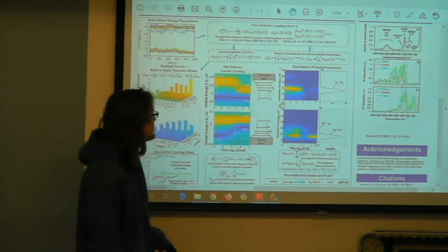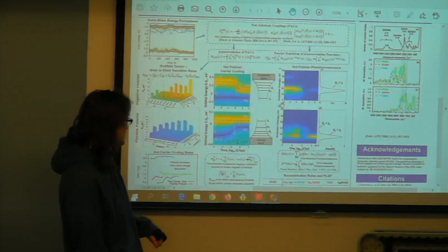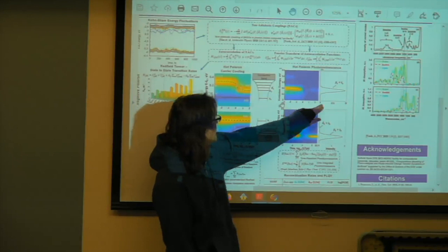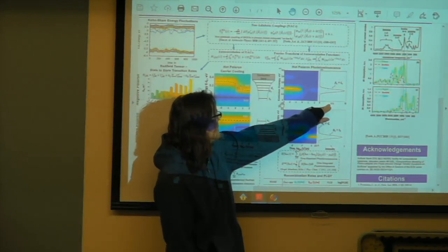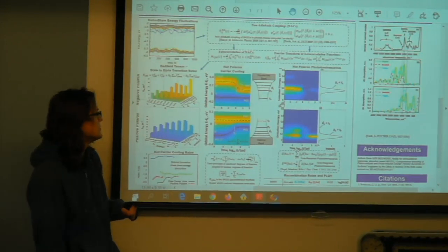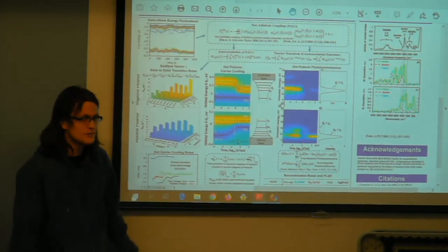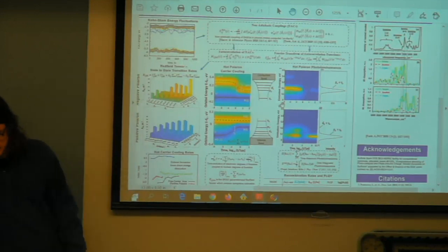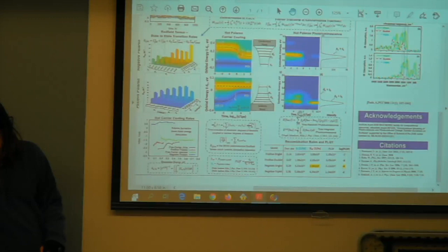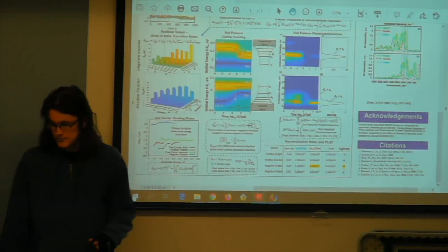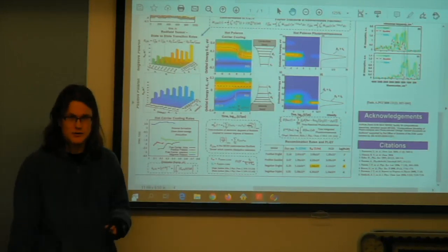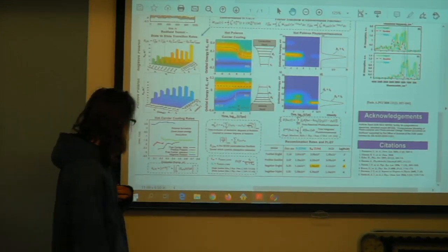Comparing the negative and positive polaron, you should look at intensity over its lifetime. Negative gives us a greater number of counts. That gives one indication that it's a better emitter than the positive polaron would be. To characterize their luminescence properties more thoroughly, we compute the photoluminescence quantum yield from our dynamics.